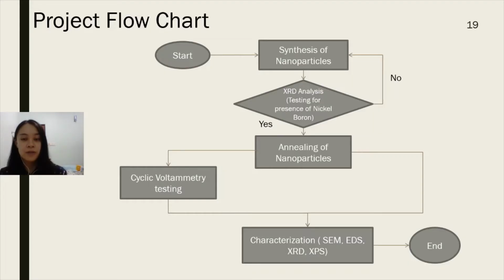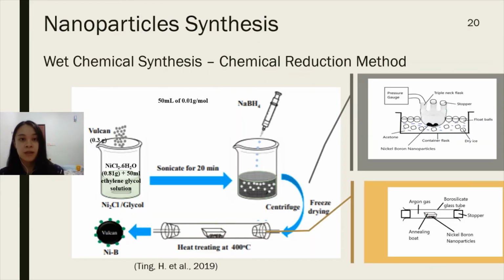So first we will start from the synthesis of nanoparticles and then followed by XRD analysis to test the presence of nickel-boron nanoparticles and followed by annealing of nanoparticles. And then we'll undergo cyclic voltammetric testing to test the catalytic performance of nanoparticles and then undergo characterization through SEM, EDS, XRD, and XPS. So for the nanoparticle synthesis, we'll be using wet chemical synthesis through chemical reduction method.